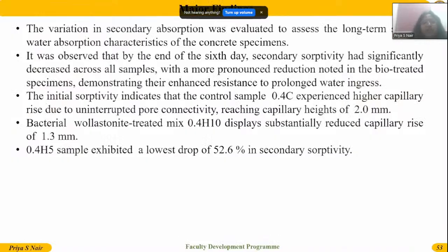The variation in secondary sorptivity, secondary water absorption, was evaluated to assess the long-term surface water absorption characteristics of the concrete specimen. It was observed that by the end of the 6th day, secondary sorptivity had significantly decreased across all samples, with a more pronounced reduction in the bio-treated specimens, demonstrating their enhanced resistance to prolonged water ingress. In the initial sorptivity, the control samples showed a maximum capillary rise of 2 mm, but the bacterial concrete showed only 1.3 mm. That was shown by 0.4 H10. Also, the 0.4 H5 sample exhibited the lowest value, a drop of 52.6% in the secondary sorptivity.